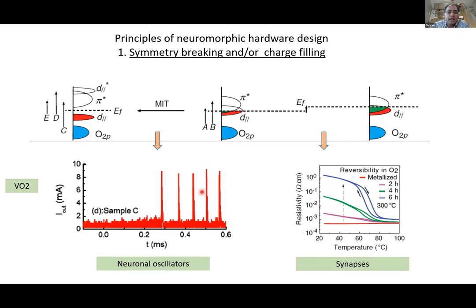Now, this is for a pristine or nearly stoichiometric material. You can also introduce defects in these compounds, for example oxygen vacancies. If you introduce oxygen vacancies, they can gradually metallize the film by donating electrons to the vanadium orbitals. And you can reduce the ground state resistance from the nominal insulating state all the way to a fully metallic state. So you can very carefully control the insulating state resistance, the phase transition threshold temperature, or effectively the voltage, and also the on-off ratio. There are many different parameters that can simultaneously be controlled.